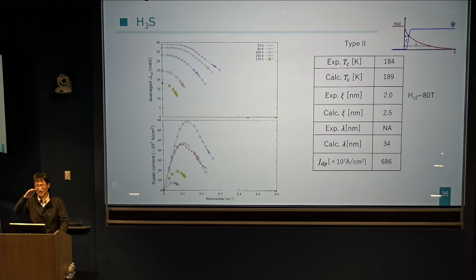HC2 is not experimentally determined, but by looking at the slope at high temperature and extrapolating to zero temperature, we can roughly estimate that HC2 is about 80 Tesla. From this number, we can roughly estimate Xi as large as 2.0. And this is consistent with our theoretical values.